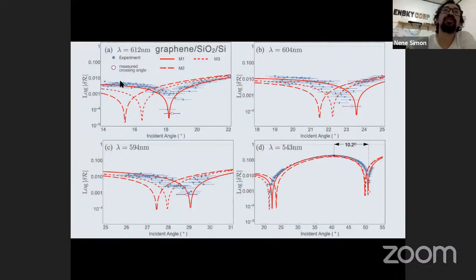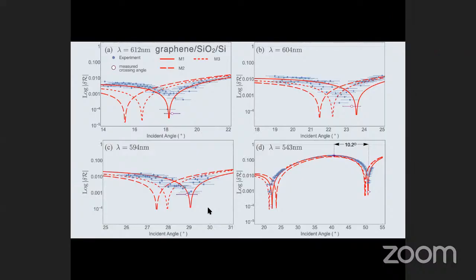Now, on all of these curves, we use the thickness of 0.345 nanometers for the graphene layer. Changing the thickness of the graphene layer would shift this dip here. The consistency of the measurements with the theoretical predictions shows that the graphene layer's thickness there is around 0.34 nanometers. So it agrees with the theoretical prediction in the literature as well as the value provided by the technical sheet. Okay, that's it for me at this moment.